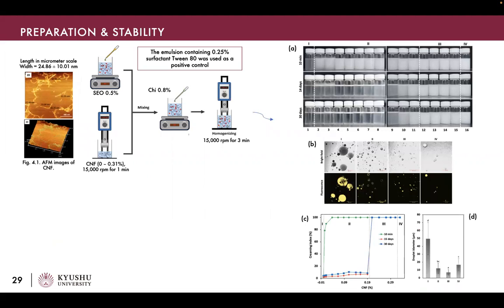Various concentrations of cellulose nanofiber were used in this research, ranging from 0 until 0.31% of cellulose nanofiber with length in micrometer scale and width about 24.86 nanometers, which was characterized by using AFM, that is used to produce Pickering emulsion solution. And then the emulsion containing 0.25% surfactant Tween 80 was used as a positive control.